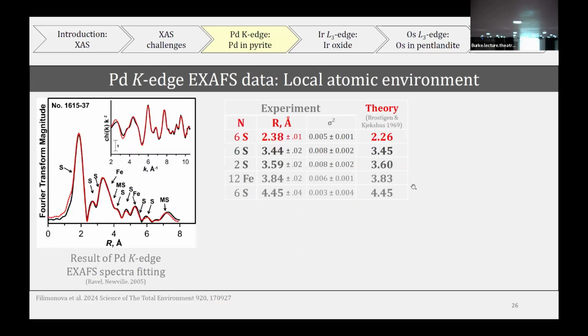Then we analyzed the local atomic environment of palladium in pyrite, and this is the fitting curve, shown with a red line. What we see here is that palladium was surrounded by 6 sulfur atoms at this distance, and comparing to the theoretical value in the pure pyrite, the distance increased. However, in the rest of the coordination shells, the distances were close to the pure pyrite.